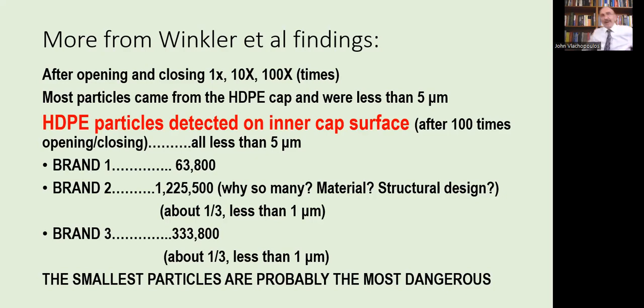So we've got a problem. How come brand 1 had only, I should not say only, but had only 64,000 as compared to 1.2 million? What was the difference in the HDPE material? What was the melt index? What was the molecular weight distribution? What were the injection molding conditions? The flash that I was talking about, perhaps the cavity gate marks, if they were absent or present, or the pressures that they were using during injection molding, whether the same or equivalent, similar, but certainly there were differences in the material and processing conditions of the caps of brand 1, brand 2, and brand 3.